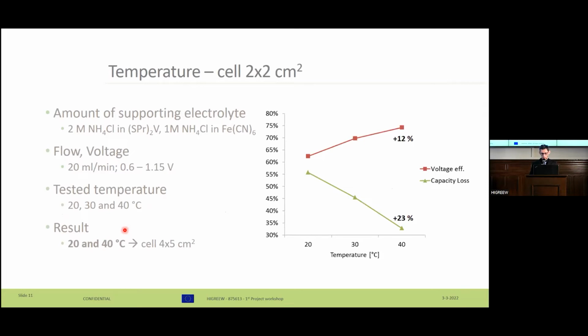On this slide, I want to show you the effect of temperature on the cell. We started with the smallest cell, and we chose the molar concentration of 2 moles per liter on the organic side and 1 mole per liter on the inorganic side. Flow rate was set at 20 milliliters per minute. Voltage was mentioned, and the tested temperature was from 20 to 40 degrees. You can see more than 20% in voltage efficiency, and mainly more than 20% in initial capacity loss.